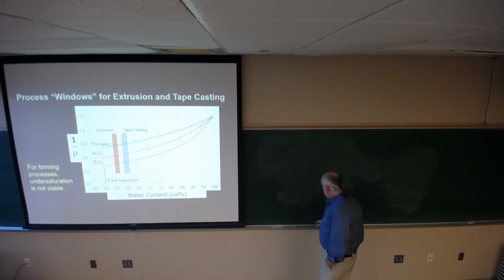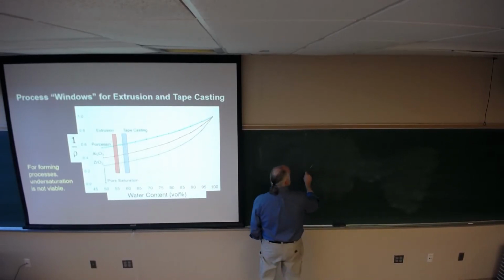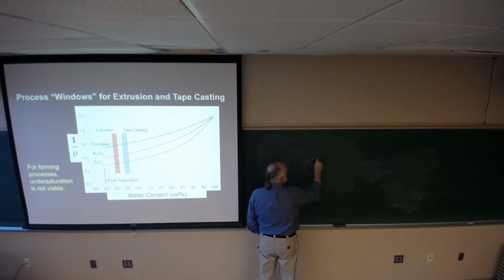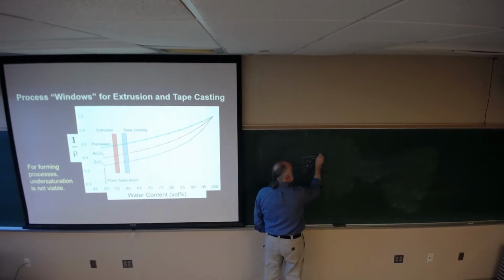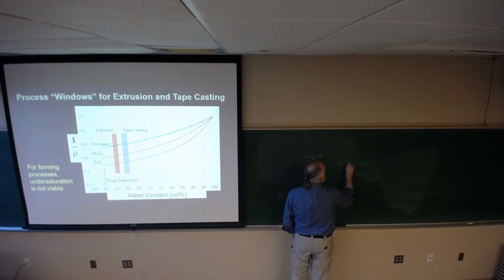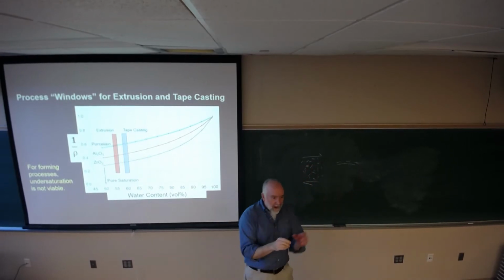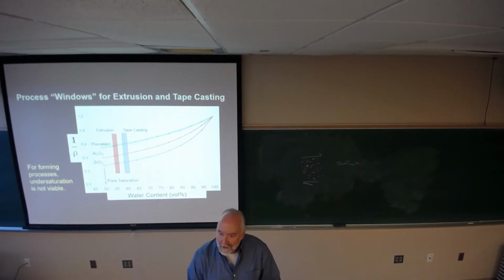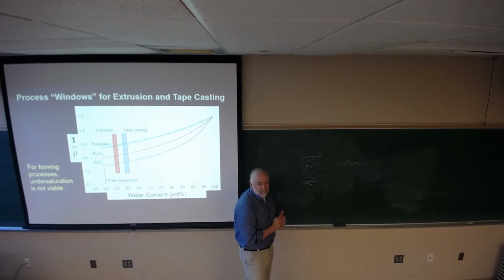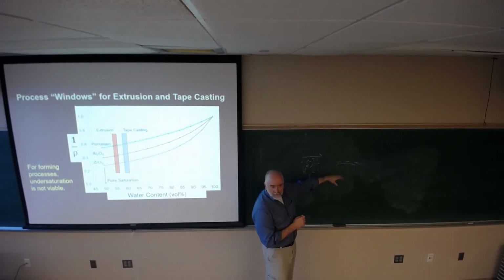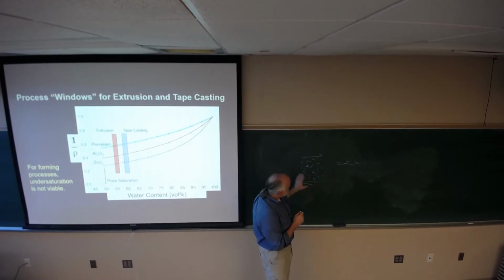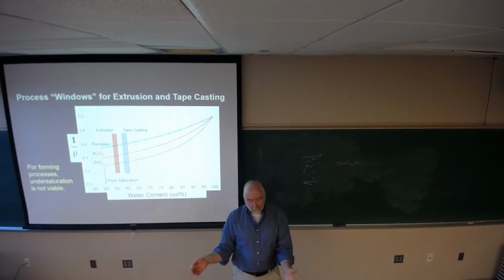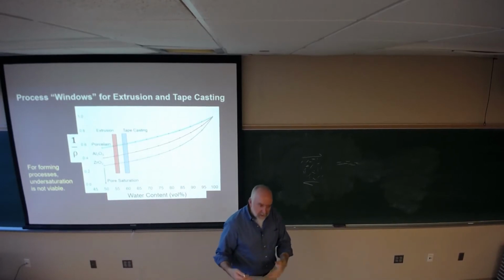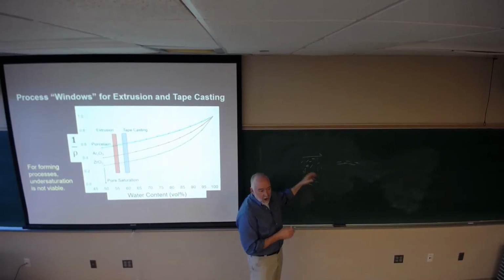So it's my argument that in clay bodies, you get randomly oriented clay particles, and they're going to pack to a certain packing efficiency. But when I shear this system, I get alignment of clay particles, and that increases the packing efficiency, producing the amount of excess water I need for plasticity. This is the intrinsic plasticity associated with clay: in shear forming, which is all the plastic forming processes, shearing creates the excess water that I need automatically to give me plastic behavior.